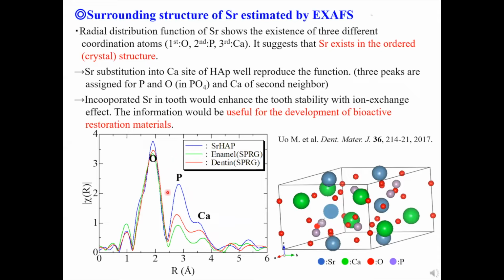Those three lines show similar coordination. We can find oxygen as the first neighbor, phosphorus as the second, and calcium as the third neighbor. Therefore, the absorbed strontium in enamel and dentin could be suggested as inserted or replaced into the calcium site of apatite.